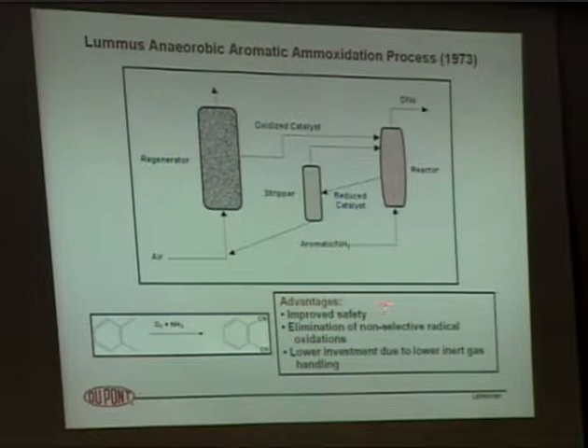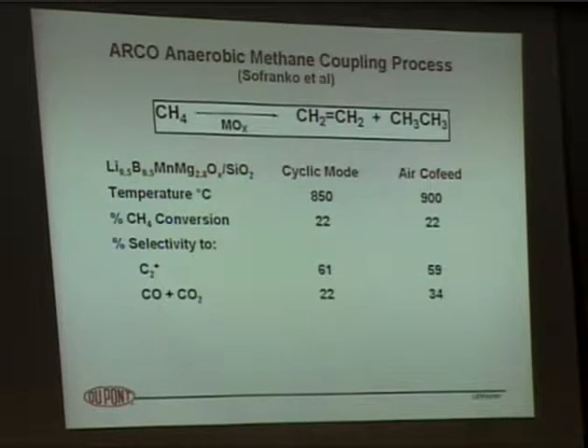They commented that it was much safer because you're separating the oxygen from the orthoxylene. The non-selective radical reactions were eliminated, so they reported very high yields, and they also said the investment was significantly lower. Now, I don't know why this did not go commercial, but it was a wonderful example of one of the first examples of anaerobic oxidations.